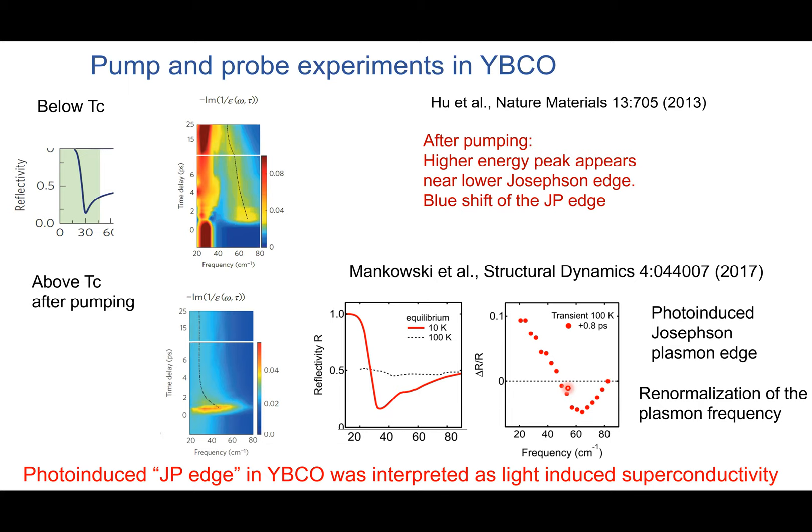How long does this whole thing last? In this specific experiment it's about picoseconds. In most of these light-induced superconductors it's about a picosecond, but there is one exception — in K₃C₆₀ it lasts at least nanoseconds, about 1000 times longer.